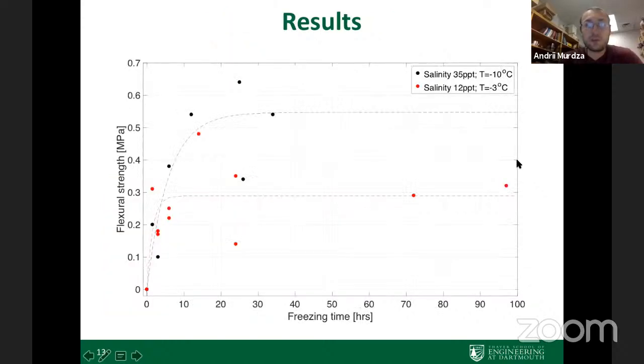So the next one, we investigated the saline bond. So we still used the freshwater parent ice, and we sprayed with a saline mist and followed exactly the same procedure. And we used salinity of 12 ppt at -3 Celsius, and we also used salinity 35 ppt at -10 Celsius. And you can see the results in red and black correspondingly.